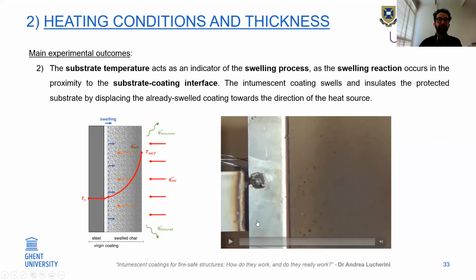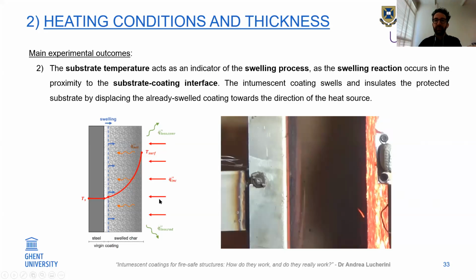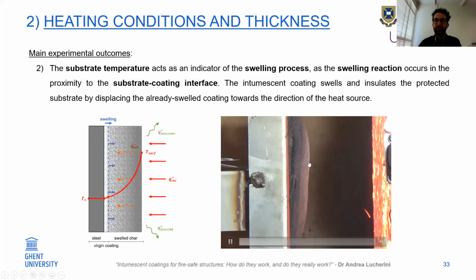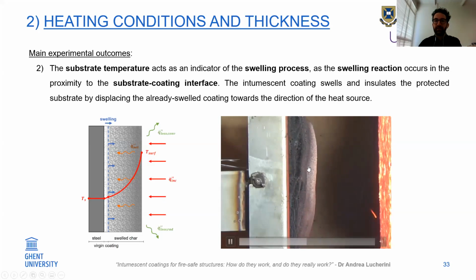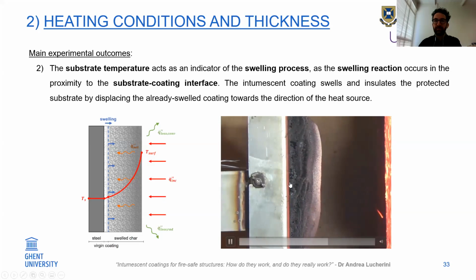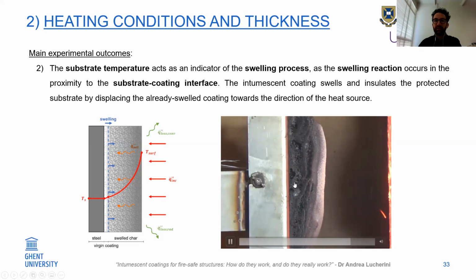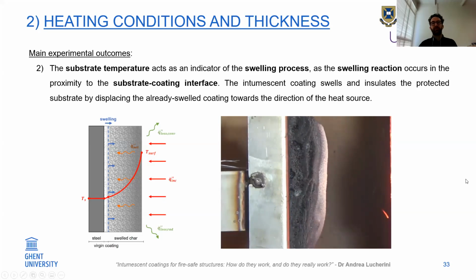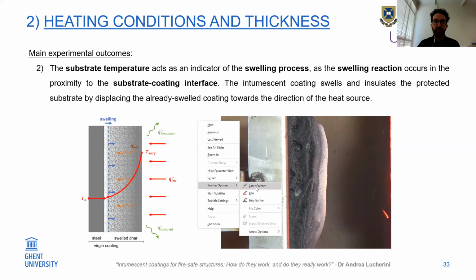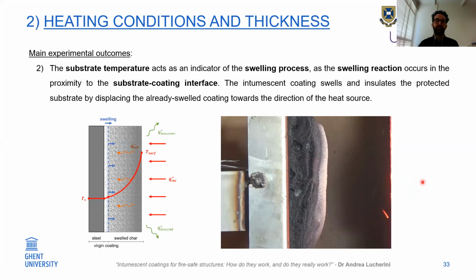the heat source. And what you can see particularly, if I zoom in on one of the experiments, you can see that the radiant panel gets closer and that the coating starts swelling. And as you can see, this part is already swelling, but then this part is sort of steady, but the swelling is pushing from here. So the coating swells very close to the substrate, where actually the reaction happens. And this is a very interesting and important aspect because it makes you understand how the swelling of intumescent coating occurs and what the physics behind it are.